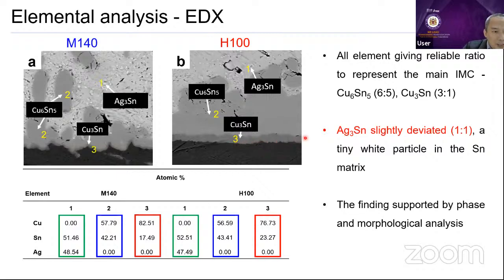The number 3 here, this line, is actually the Cu3Sn, between the copper and the Cu6Sn5. Normally, when we run reflow, they start to form Cu6Sn5. But if you have enough time and temperature, sooner or later they will form another one. It's good to have this layer, but sometimes a thick layer is not good for the mechanical properties, because this one will be the cause of failures, right?